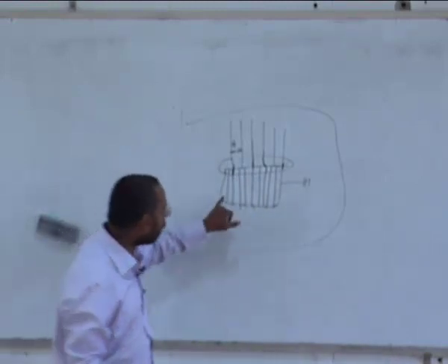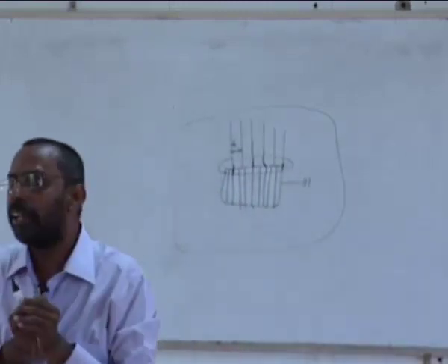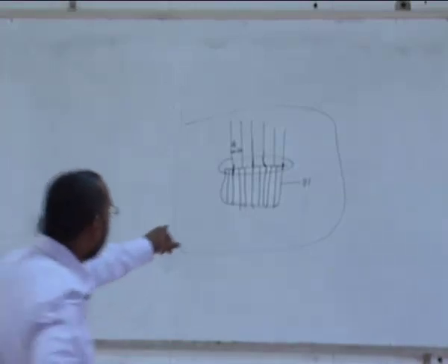Though there are no dislocations, the number of planes in a particular distance and the number of planes in a particular distance here are very close to each other. And as a result, no dislocations are forming. But because of the matching that is forced on it, there is a bending of the planes. And then you get what is called coherency strains.